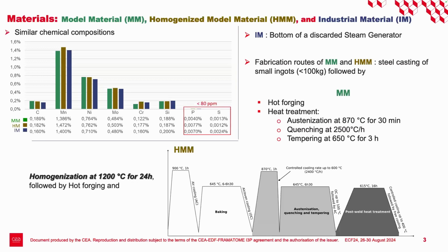The MM material has followed classical hot forging and then austenitization, quenching, and tempering, while the homogeneous model material has been exposed first to a homogenization heat treatment at 1,200 degrees C for 24 hours, and then a quite classical heat treatment, as you can observe in the industrial material.